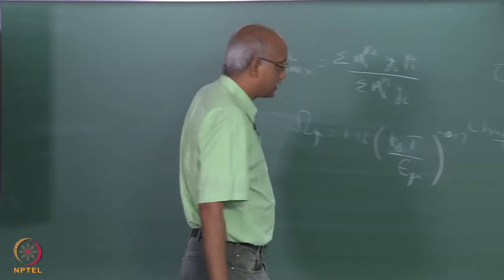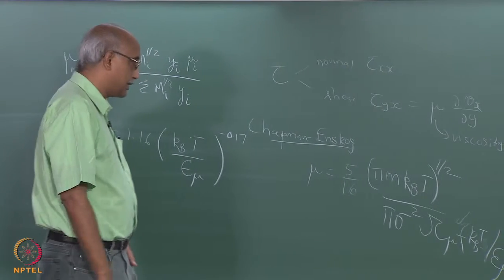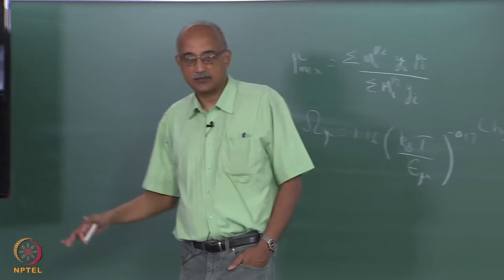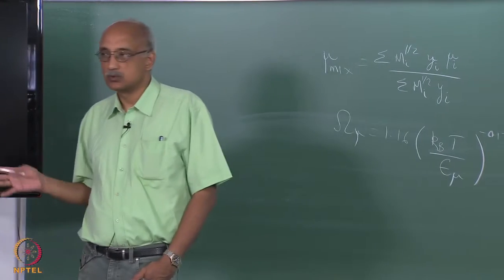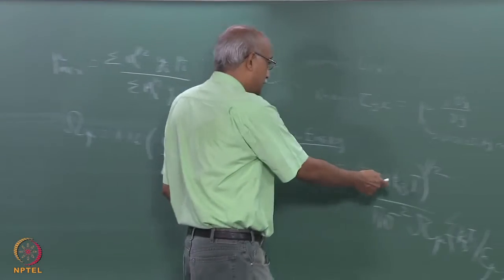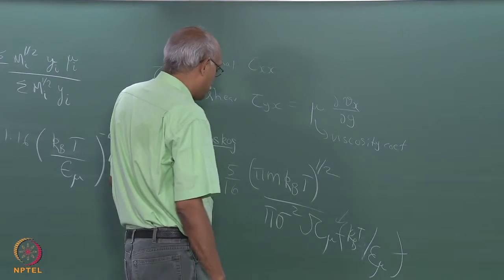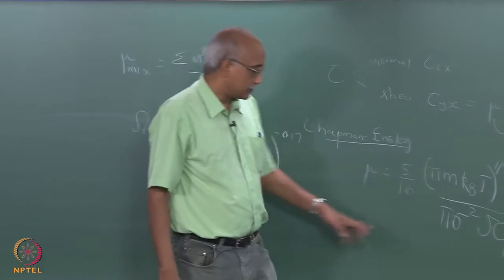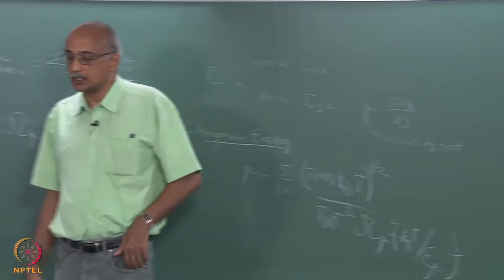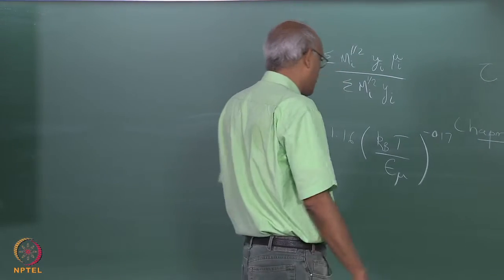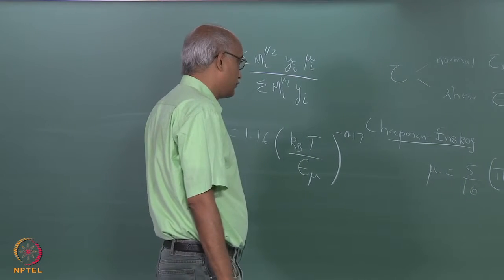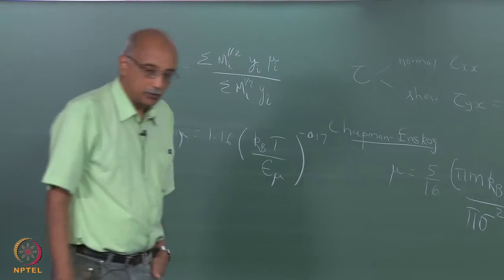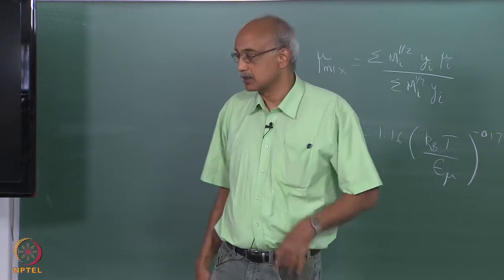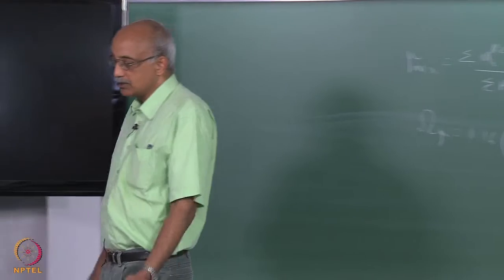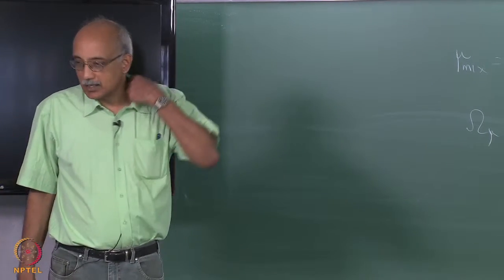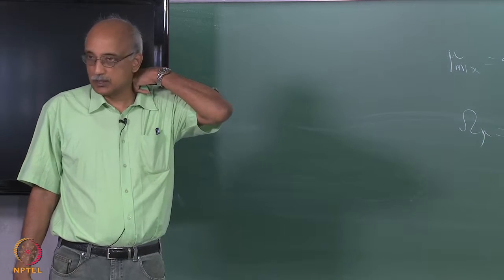If you look at the temperature dependence of mu, you can see that for a gas, the temperature dependence is fairly weak. It is about 0.5 to 0.8, because according to this, you have a T to the power half dependence, but there is also a temperature dependence that is built in here. And so, the net effect is actually a fairly weak dependence of mu on temperature. Of course, for a liquid, you know that the viscosity has a significant dependence on temperature. As the temperature increases, viscosity will decrease, and again that depends on the activation energy for fluidity of the fluid.